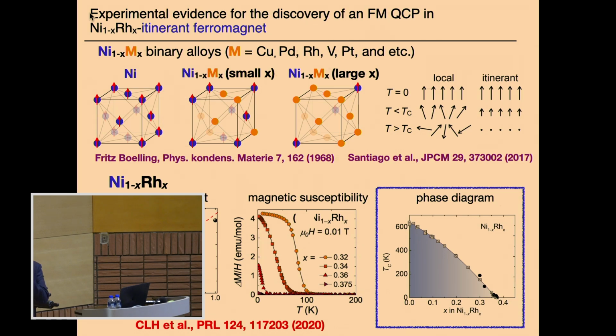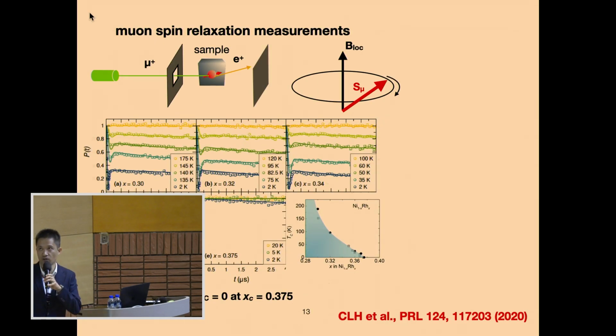If you think about the entropy between here and this state, there is a huge entropy change from here to here. That's why in specific heat we can see a transition. Specific heat probes how much entropy is changed. But if you look at the right-hand side, the entropy change from here to here is almost zero. That's why in most itinerant magnets, you can't use specific heat or magnetization to probe the magnetic order precisely. Then how do we know that our transition remains second order up to this point? So we use muon spin relaxation. We shine muons on the samples, and by measuring how muons decay, we can get the data and calculate the important parameter, which is called